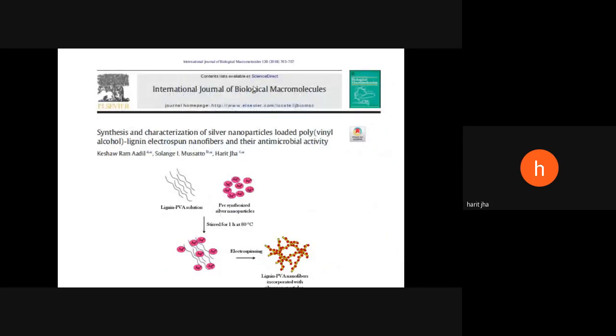This is another recent work in which the synthesis and characterization of silver nanoparticles loaded with polyvinyl alcohol, lignin electrospun nanofibers, and their antimicrobial activity was seen, in which we have used the lignin and polyvinyl alcohol solution together and the pre-synthesized silver nanoparticle. They were then, after interaction at 80 degrees, subjected to electrospinning, by which the lignin PVA nanofibers were formed. Okay.